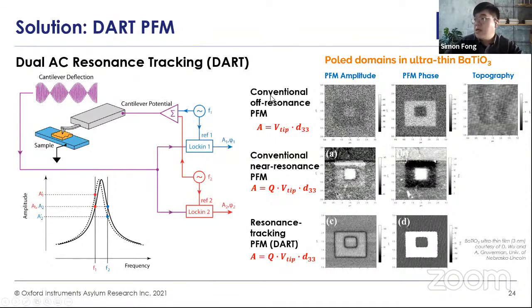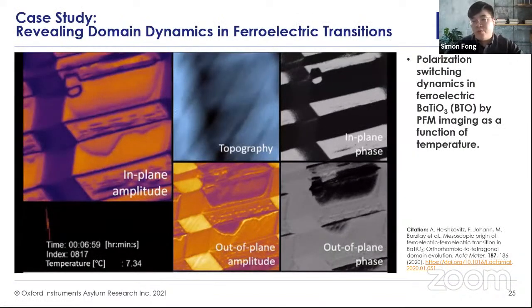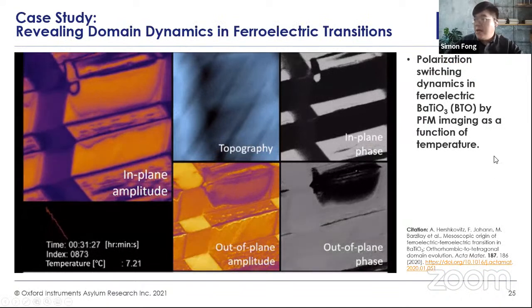You can see a conventional measurement, only changing the tip voltage. You can still get the phase, but it's a little bit noisy. With the conventional contact resonance image, you get a good signal, but again, you get instability in the imaging. But combining these both with DART, you get a clear and sharp image, very good signals, and also clear domain images. So that is basically the golden, go-to method for AFM.